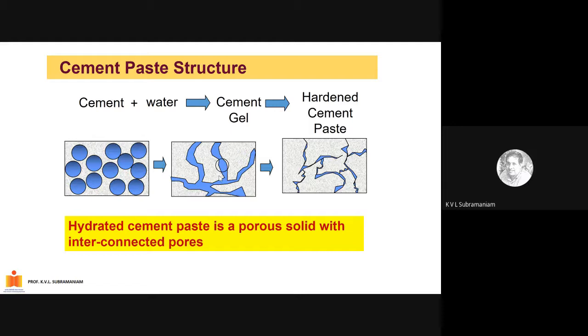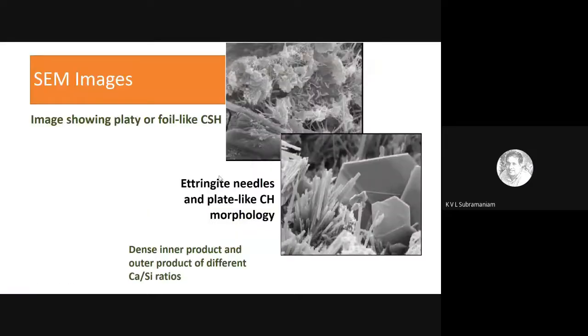So the diameter of the pores, the volume that is available with water, starts shrinking. Now, just to show you the complexity of this material, once it hydrates, if you look at it under an SEM, a scanning electron microscope, it is very confusing. So this is what typically awaits you. The calcium silicate hydrate itself is basically an amorphous material. It does not have a defined structure.